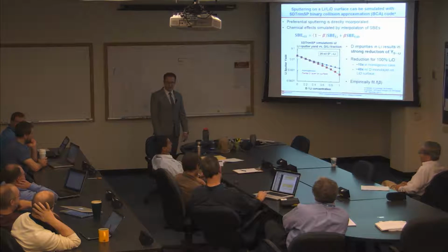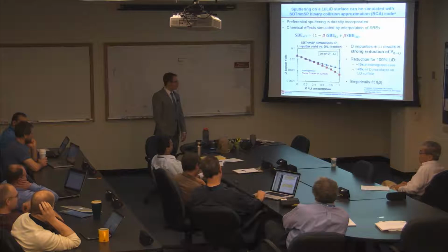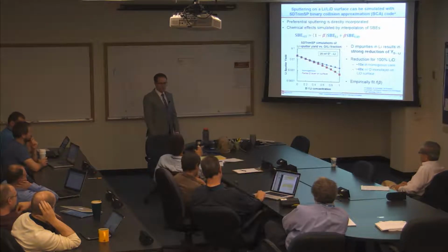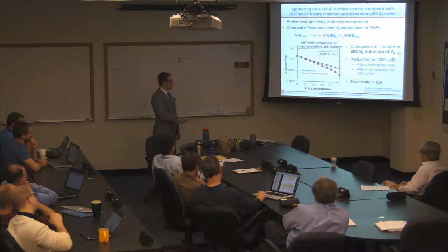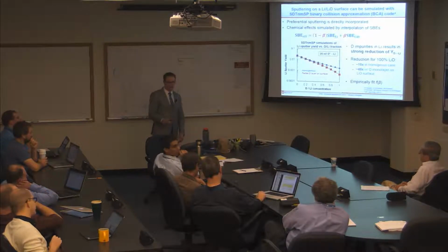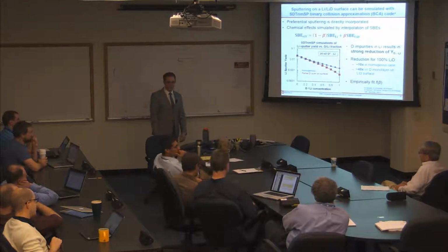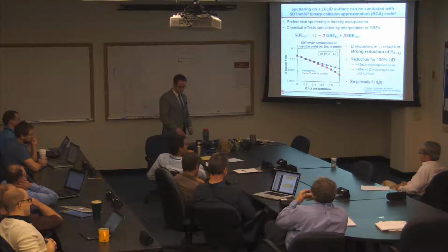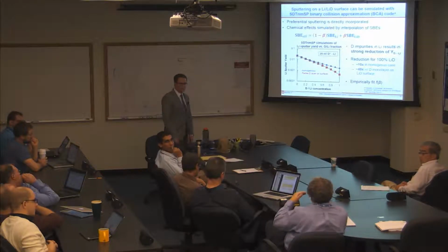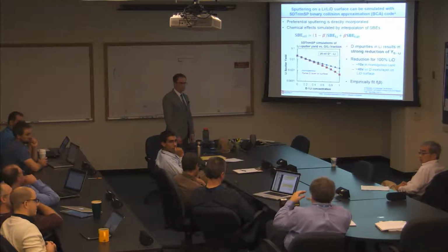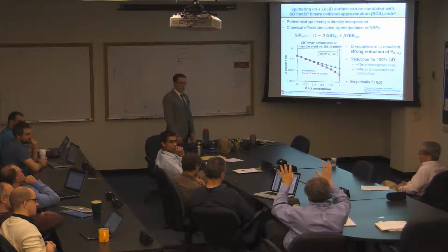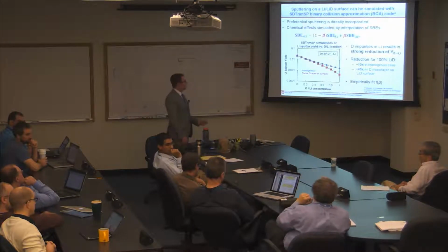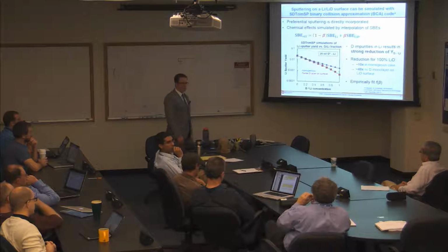Well, part of that would just mean there wouldn't be any lithium. Sure, yeah. Your model already takes into account supersaturation of the surface, basically. Right, the red curve is taking into account supersaturation of the first monolayer, but you're assuming that under the first monolayer you can't have more than a 1-to-1 deuterium to lithium concentration. Sputtering also has this complicated thing where the particle comes in, goes down a few monolayers, comes back up, and really it's what blows off on its way up that matters. Yeah, but this was done with the BCA code, so that's all taken into account.